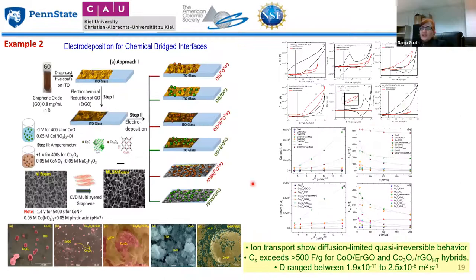So that was, in the second example, we have used the electrodeposition chemically to allow, as I showed you, the interaction of these nanoparticles with the graphene, because we wanted a covalent interaction so that it makes the bond, the nanoparticles or transition metal oxide nanoparticles to the graphene. So we use the electrodeposition, which allows the chemical bridging of this interface rather than a physisorption. Although we have compared with the physisorption, we have found that if we have a chemically bridged interface, it definitely shows a higher response.